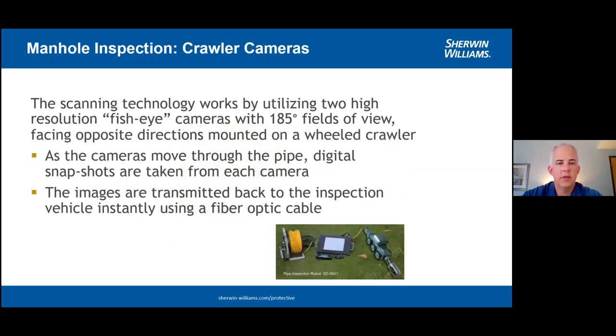There's also crawler cameras. These are fairly expensive. They're becoming more and more common, but this scanning technology works by using two high-resolution fisheye cameras facing opposite directions on a wheeled crawler. As the camera goes through the pipe, down the hole, digital snapshots are taken, and this actually allows you to go up through the sewer collection pipe itself in between the manholes, going a little bit beyond what we can do just looking in the manholes and wet wells themselves. Everything's instantaneous. There's a fiber optic cable coming back to, again, the van or the pickup where the monitors are set up.